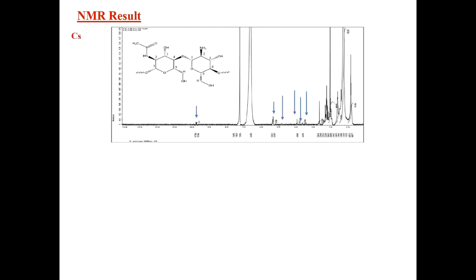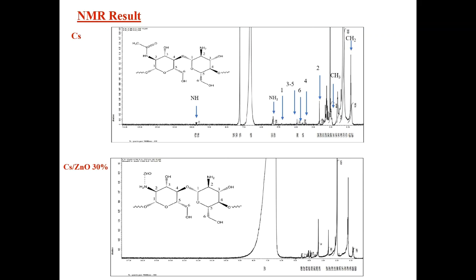Chitosan zinc oxide samples were also subjected to nuclear magnetic resonance measurements for proton NMR. The main characteristic peaks of chitosan protons appeared as shown. For chitosan zinc oxide, the peaks suffered from broadness and all the peaks related to completely deacetylated chitosan, with disappearing of the CH3COO group and NH changed to NH2. In addition, protons of NH2 disappeared, an indication of coordination between zinc oxide and chitosan through it, and the broadness of the peaks is an indication of metal presence according to paramagnetism, which confirms the coordination of zinc oxide with the NH2 group as the FTIR result indicated.